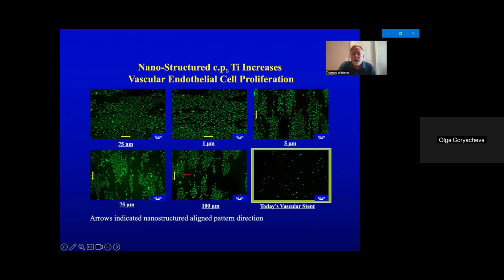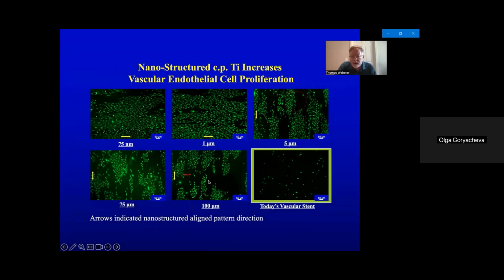In the same study, we created nanotextured features on titanium. By using an anodization process, we created linear patterns of those nanotextures indicated by these arrows. The size of those features are indicated below each fluorescent image. And you can see that by going from a large feature size down to smaller, we were able to cover more of the stent with endothelial cells. And that creates for a more effective stent, a stent that is less recognized by your inflammatory system to reject it. So this is another example of how nanotexturing can be used in the cardiovascular space.